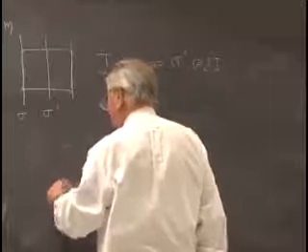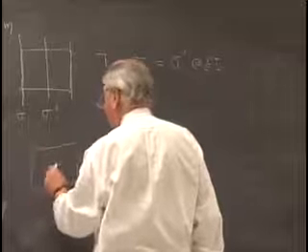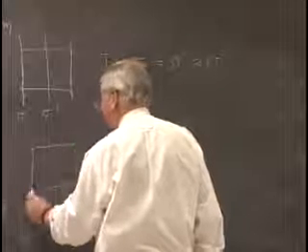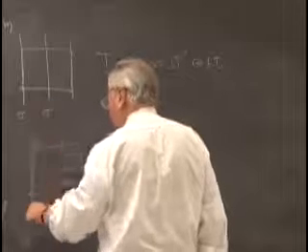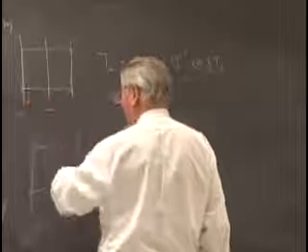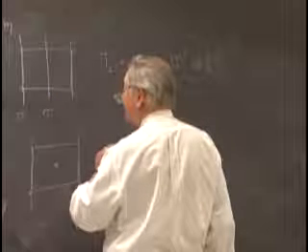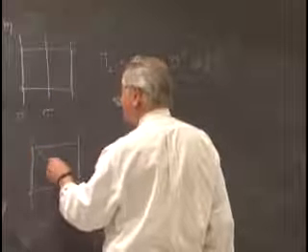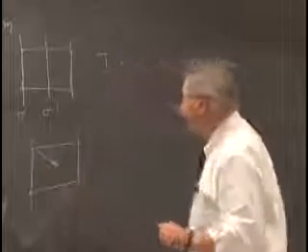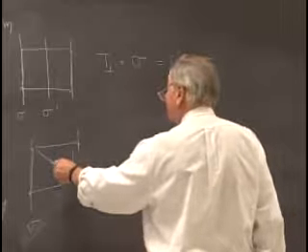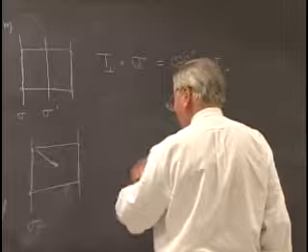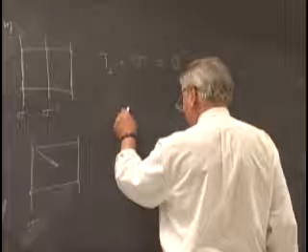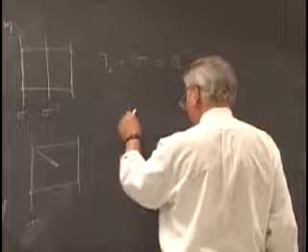When we combined a mirror plane now with the centered rectangular net, we'd have all of the mirror planes that we'd have here because this primitive rectangular lattice is a subgroup of the centered lattice. And then the interesting thing happened when we combined the reflection operation sigma with this translation that went to the center of the cell. And that gave us a transformation that was something we had not encountered before.